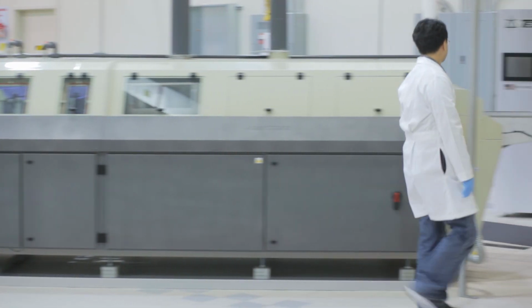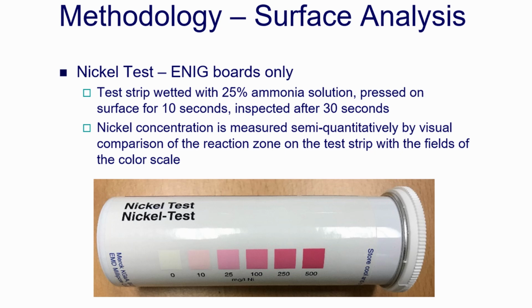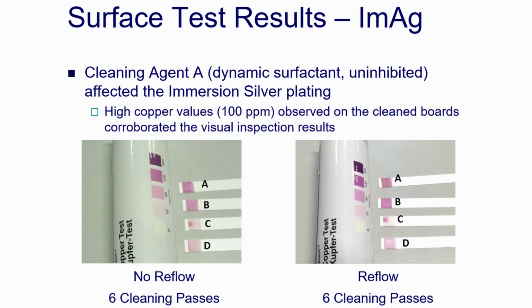The next analytical test conducted was a surface analysis test using a copper test and a nickel test. For immersion tin and immersion silver, a copper test was conducted on the plating, which would detect any exposed copper after the cleaning process. It was found that for immersion tin, there was no exposed copper detected, which means that the cleaning process was fully compatible with the immersion tin plating. This was true for all four chemistries tested. In the case of immersion silver, three of the chemistries were fine with no higher levels of exposed copper detected, whereas the one chemistry which showed deterioration in the visual inspection also showed higher amounts of exposed copper, and that proved that the plating is getting affected by the cleaning process.